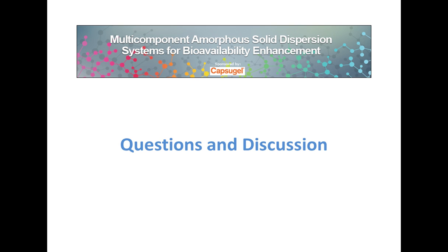Now, what are some of the deciding factors when choosing which multi-component architecture to evaluate, ternary or external? This is a good question, and I can answer based on what we talked about a little bit earlier. For some applications, the mechanism of how the SDD dissolves is going to tell you what architecture you need to use. We talked about today the example of drug X and TPGS in a PVP-VA dispersion. The TPGS wouldn't have been effective externally in this case because the phase separation is generated inside the SDD particles, not outside.